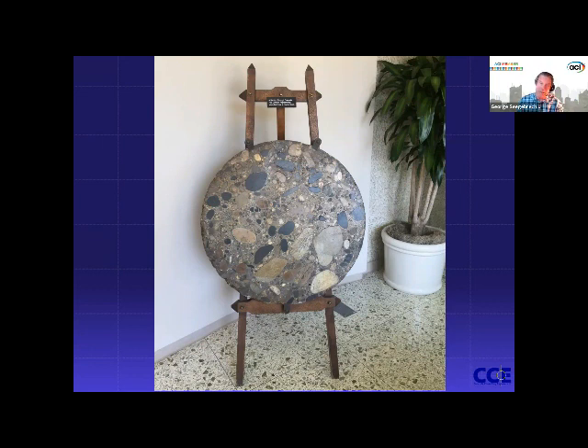And then they also used some reduction in cement content and replacement with some SCMs at that time. But the larger aggregates now reduce the cement content, and yes, it saves money, but it also reduces the heat of hydration without detriment to the structure. So very cool. And the photos of the cylinders, their cylinders were 3 by 6 feet. And they cast regular size ones too. Regular to them was like 9-inch diameter, was the smallest one. But read the paper. It's really fascinating, and it's just another approach on how you're handling massive concrete. By the way, this aggregate size was for the dam. For this job, it was nowhere near that large. So a thermal control plan was a necessity.